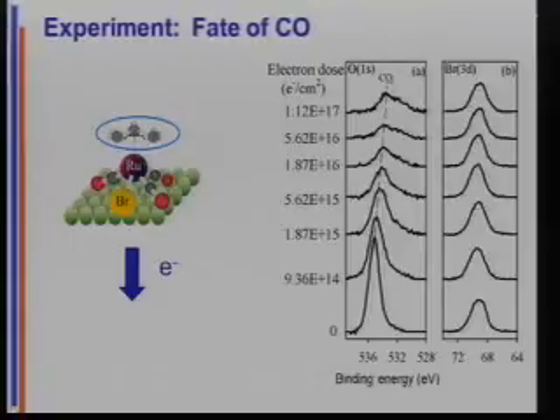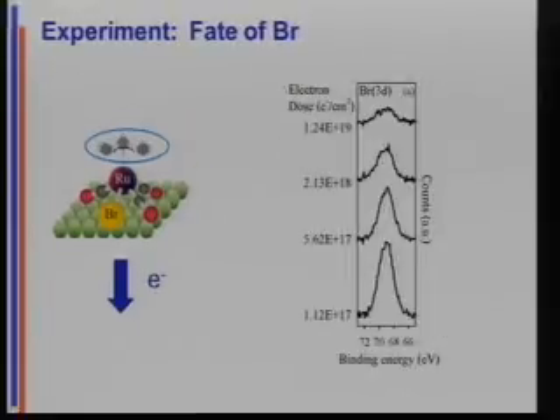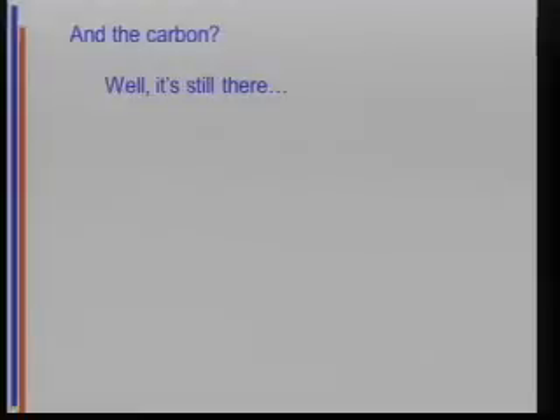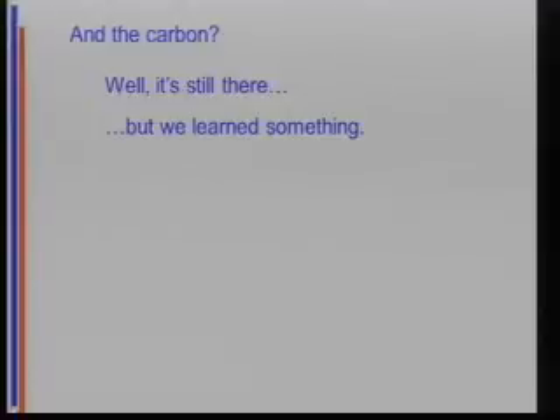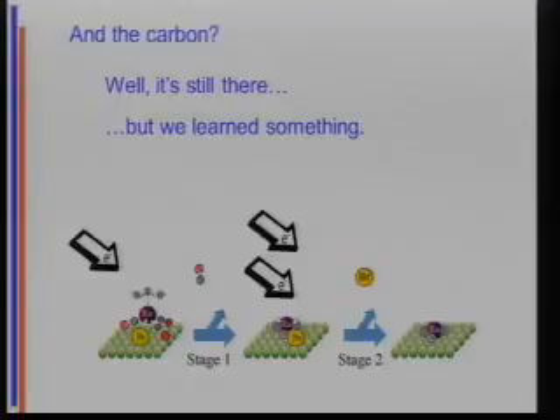The bromine is still here, okay? But look at these electron doses. This is 10 to the 14th to 10 to the 17th electrons per square centimeter. If you keep beating on this with electrons, here's 10 to the 17th to 10 to the 19th, you start getting rid of the bromide. So we can knock the halide off in post-deposition processing. And then we talked them into doing a gold substrate so they could actually follow the carbon. Yeah, well, the allyl group is still there. Okay, the carbonyls are gone. But we learned something. We learned something about carbonyls, and we learned something about halides. Okay, so in stage 1, we get rid of carbonyls. In stage 2, we get rid of bromides.